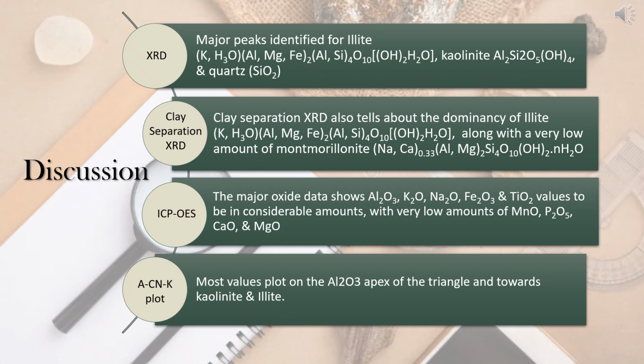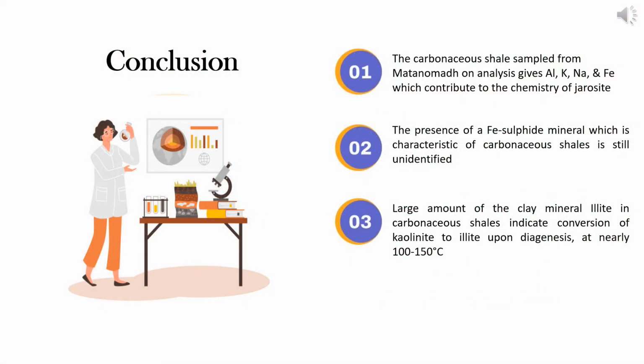The A-CN-K plot also shows that shales contain a very small amount of sodium in them, and the majority of samples plot on the illite kaolinite side of the triangular plot. The study conducted on carbonaceous samples leads to the following conclusions.